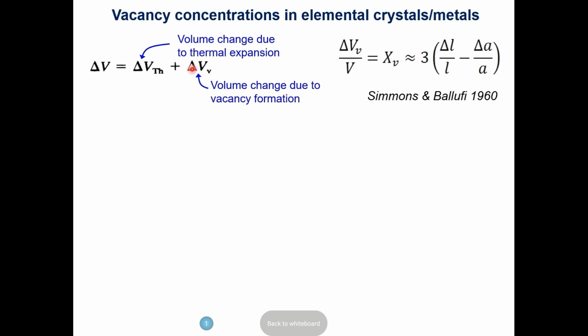This volume, defect related volume change, if normalized by the total volume of the example, can be related to this fractional vacancy concentration. For an isotropic solid, like a cubic crystal, it can be approximated as 3 times the change in dimension length, delta L over L, minus a term that introduces a change in the lattice constant. So the quantity you're looking for, this fractional vacancy concentration in your material, can be calculated or estimated by looking at the dimensional change of your sample.